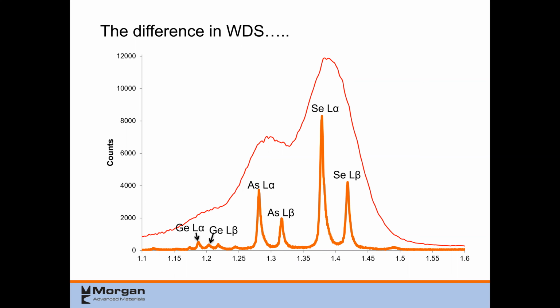And WDS is really cool because you can even see some of these minor lines. Like I was talking about, certain minor lines correlate to which electron from which shell dropped in to fill that gap. And I can actually pinpoint a lot of those using WDS.